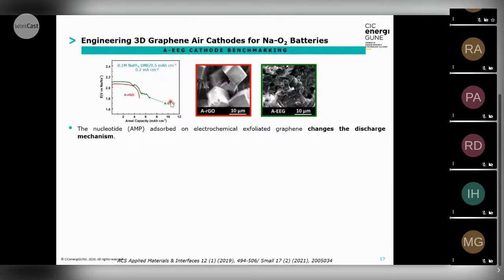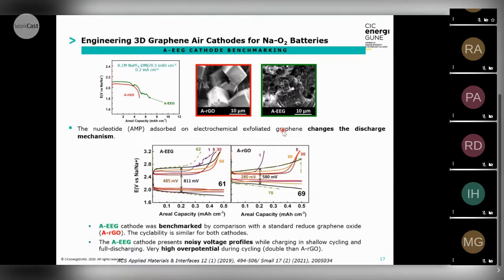So first, what we did was just discharge this material in this electrolyte, under this condition, using sodium metal, and we can see that the discharge capacity of the electrochemical exfoliated graphene is higher than that of reduced graphene oxide. And surprisingly, the deposition mechanism is also different. In the first one, we have these big cubes on the surface of the graphene, but in the case of the electrochemical exfoliated graphene, we have these small cubes all over the surface, meaning that the mechanism is different.